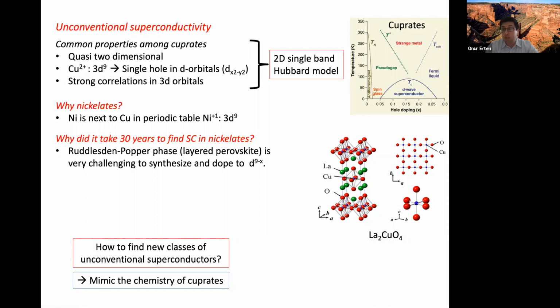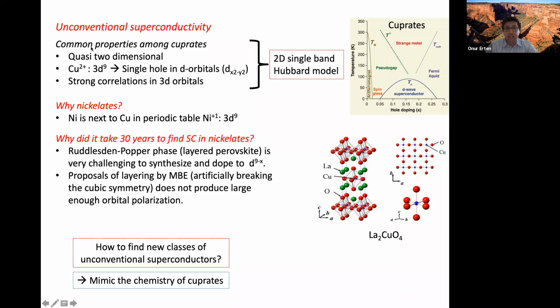So it turns out that this is a really, really challenging task. And even though it's been tried many times, clean doped samples have not been successful. There are definitely people who have been trying this for many years. And there are other proposals of creating these properties by artificially making thin films using molecular beam epitaxy, layering different nickelates layer by layer that would artificially break the cubic symmetry.